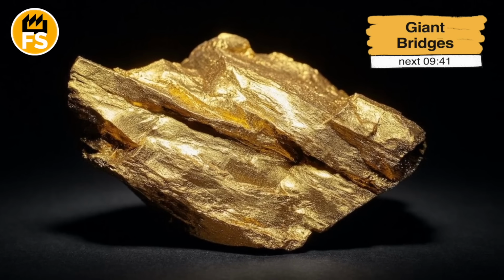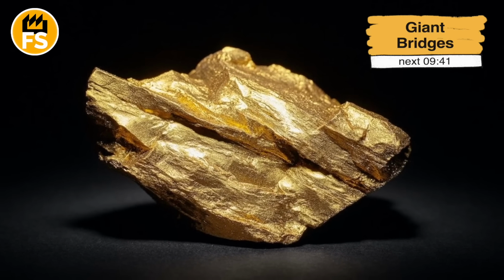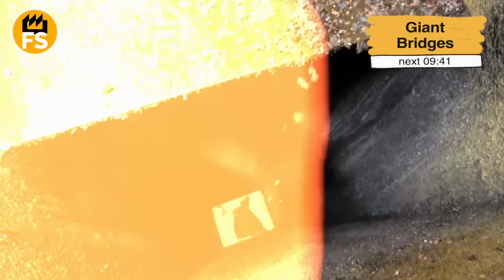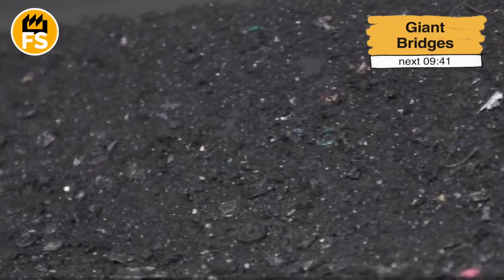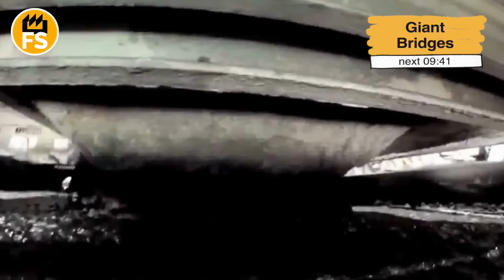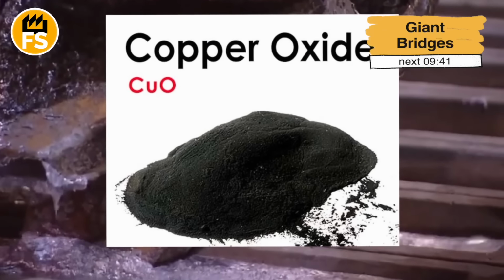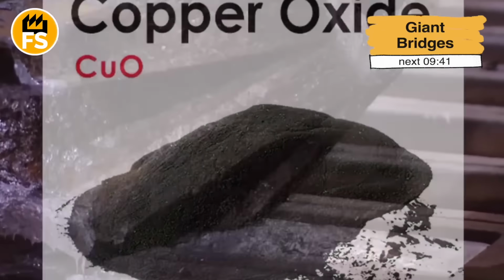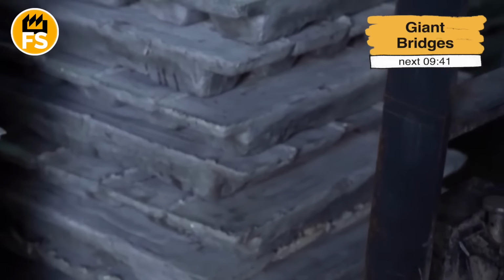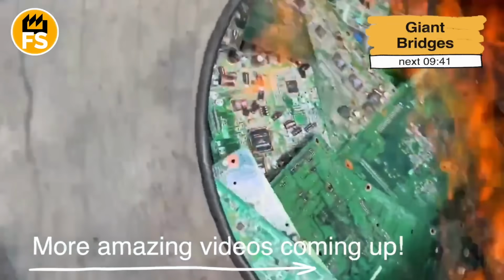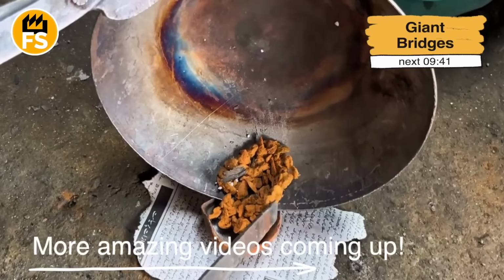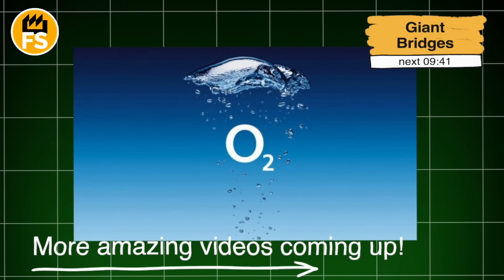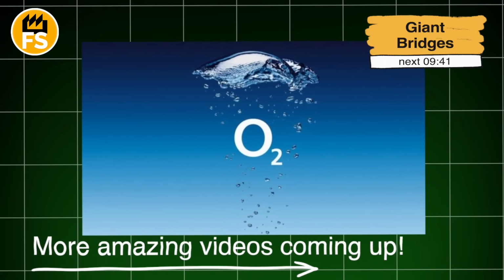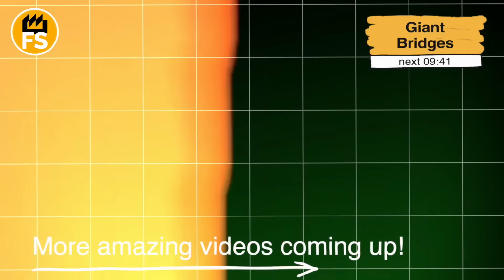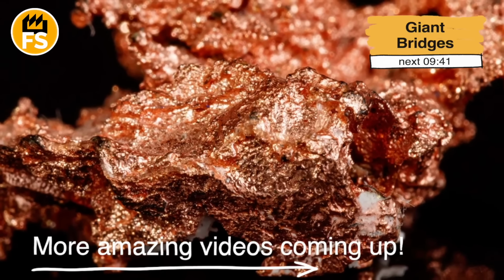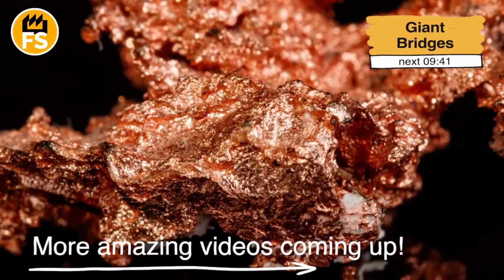Gold, like other precious metals, has a high affinity for molten copper or lead. Therefore, during smelting, gold dissolves in larger volumes of molten copper or lead, forming a so-called black copper or lead alloy. This alloy is then separated from the lighter slag. The alloy can then be further purified in converters, where air or oxygen is blown through the melt to oxidize the remaining base metals, which then pass into the slag. The output is an enriched alloy containing copper and all the precious metals.